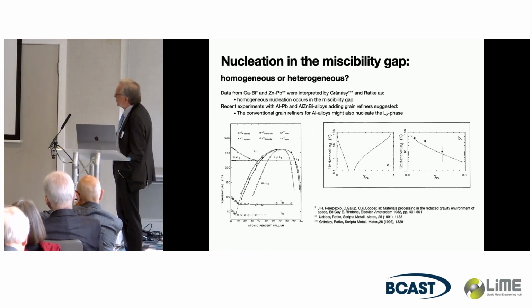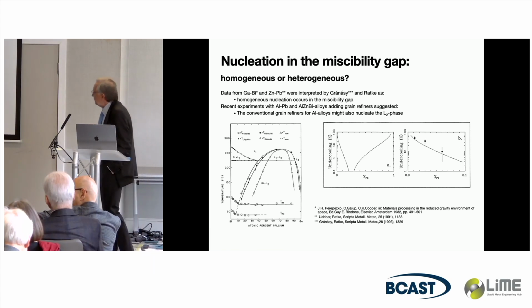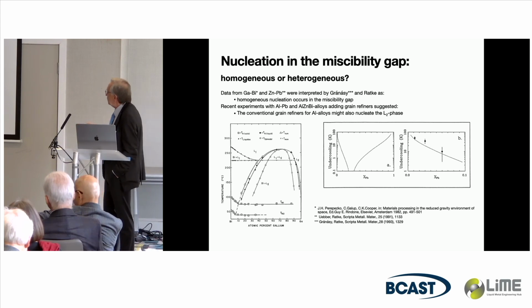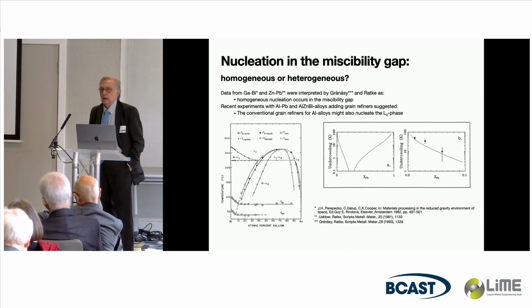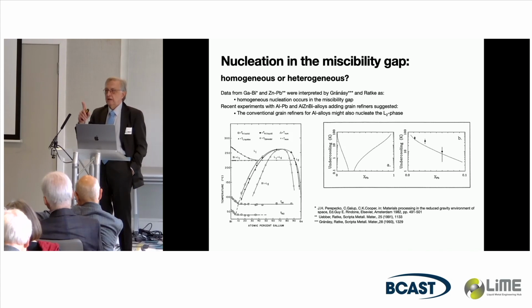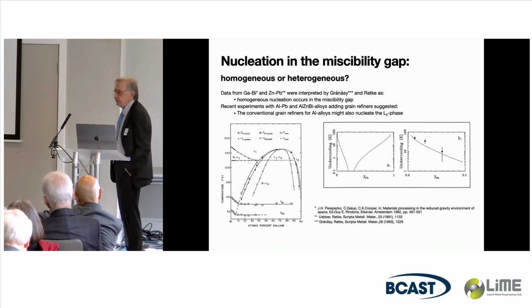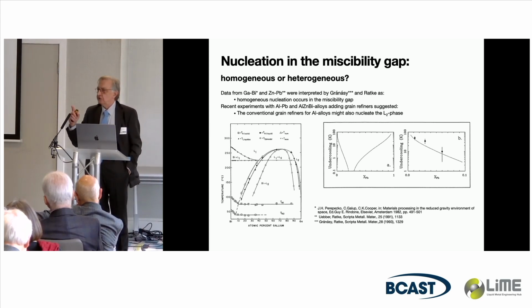And here they could show that in gallium bismuth, that's the miscibility gap here, on the side of gallium there's almost no undercooling, but on the side of bismuth there's a huge undercooling, a few 10 degrees Kelvin. And we measured the same with zinc lead, and we could show, yes, the droplets appear with an undercooling of 10 to 50 Kelvin, and Laszlo Granasy was at that time at DLR, and he said, well, I can model that. I take the model of homogeneous nucleation, and I calculate that, and this is my calculation. So we had the idea, well, that's homogeneous nucleation.